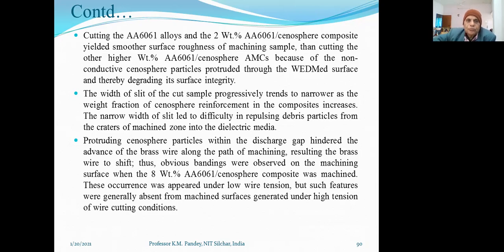We can see that the width of the slit of the cut sample progressively trends to narrower as the weight fraction of cenosphere reinforcement in the composite increases. The narrow width of slit led to difficulty in repulsing debris particles from the craters of machine zone into the dielectric media.